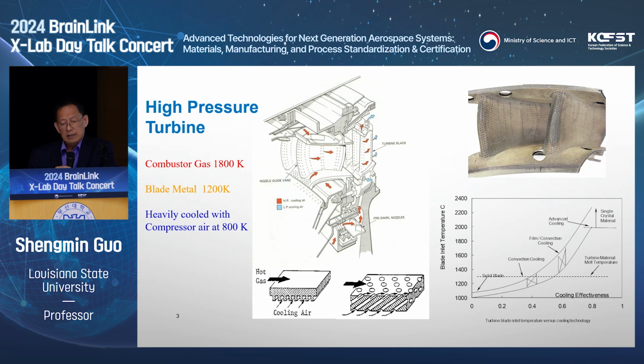There are several technologies. Material development, that's one thing. Over the years, we have had the development of the super alloys, and now you can find a single crystal blade. The entire blade is made of single crystal, nickel-based super alloys. But even with nickel-based super alloy material, it will not be able to survive under jet engine working conditions because the temperature is so high. Nickel-based super alloy single crystal will melt, will lose mechanical strength very quickly.